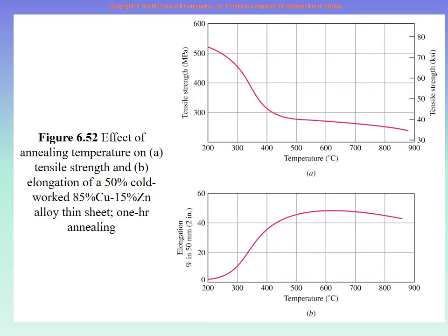So if you anneal at a higher temperature, then it goes down. But after a certain temperature, roughly 500 Celsius, if you do annealing at higher temperatures, there is almost no advantage, right? From about 200 to about 400, 500, there is a major difference. But after that, the reduction in the strength is too low. So therefore, we should not do annealing at 600, 700, 800 for this. We should maximum do it for 300, 400, right?